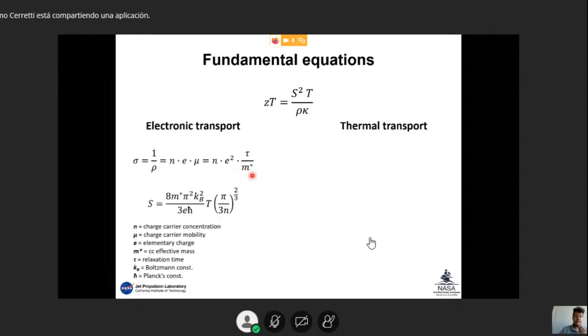But then we can see that to get better electronic properties, at least electrical conductivity, what we need is a high charge carrier concentration, but with a low mass. But that's exactly the opposite of what we need to have a high Seebeck coefficient. On the other side, we have the thermal conductivity, which is the sum of the electronic part and the lattice part. The electronic part stands for that part of the heat which is carried by electrons and holes.